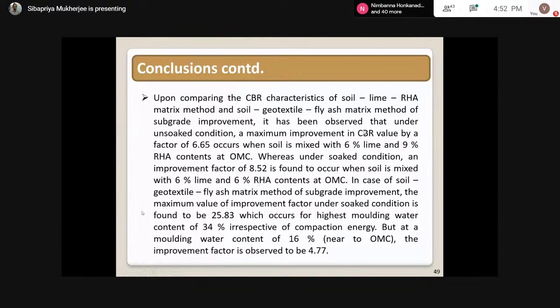In case of the soil geotextile fly ash matrix method of subgrade improvement, the maximum value of improvement factor under soaked condition is 25.83, which occurs for the highest molding water content of 34%, irrespective of compaction energy.